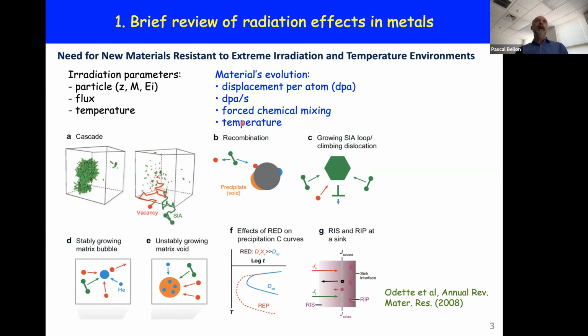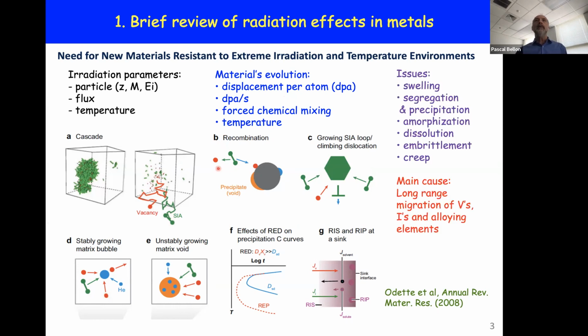These point defects and the mixing lead to potential damage. The most beneficial thing would be for those to recombine, and then interstitials and vacancies would disappear. But in reality, they do not, or not all of them do.